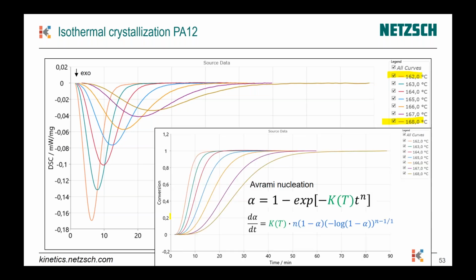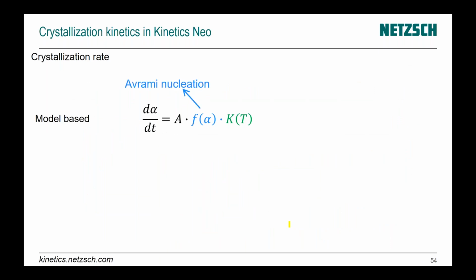Then we can recalculate it to conversion and apply Avrami nucleation, where alpha, the degree of conversion, is 1 minus exponent of minus a constant times time to the power n, where n is the dimension of nucleation. K is a value that is different for each temperature - it's a decreasing function.